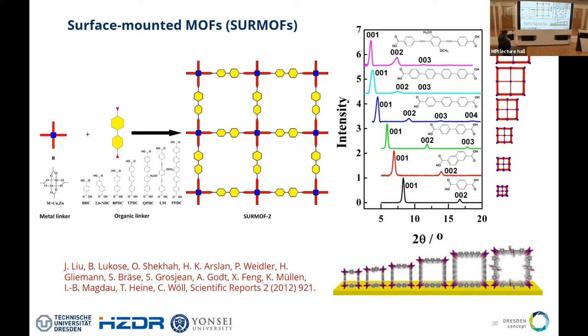And what is that? So you have here two metal atoms. They can be copper, zinc, and many others. I will only talk about copper today. And they can be arranged in a way that they can connect in four directions. And you can put a linker in between, and that can be a linear molecule. Right? And that linear molecule may have a certain length. And then you get this beautiful square lattice here, and that grows up here on the surface. And depending, I mean, these are experimental X-ray diffraction images, not powder, but X-ray diffraction images.